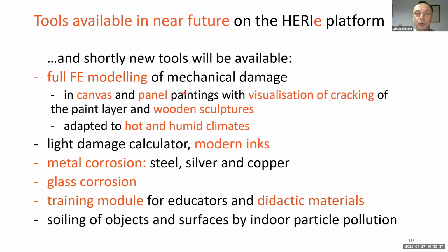You will be able to simulate, using the finite element module, your object, like canvas painting or panel paintings, and we are adding the visualization of the cracking, how the risk could be interpreted in terms of crack densification. And we are also adding large wooden objects, which is an important risk for, for example, wooden sculptures. The model is adapted to hot and humid climate, which means the material properties depend not only on relative humidity, but also on temperature.